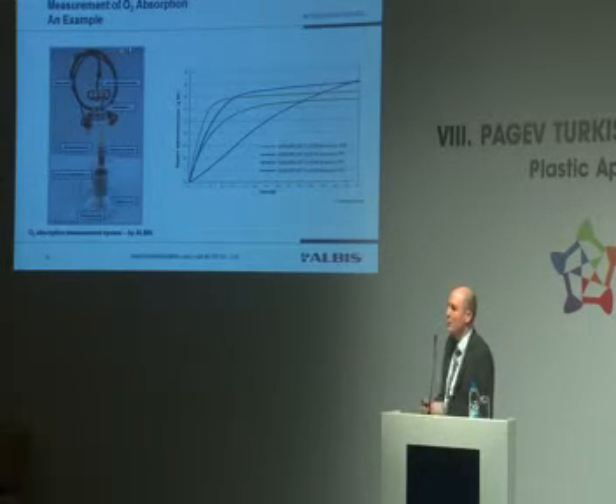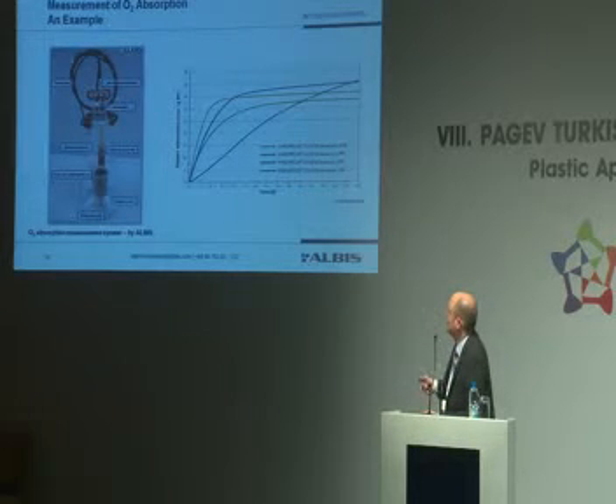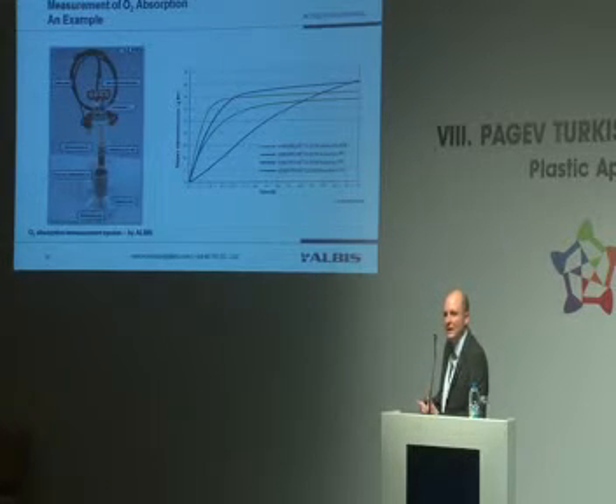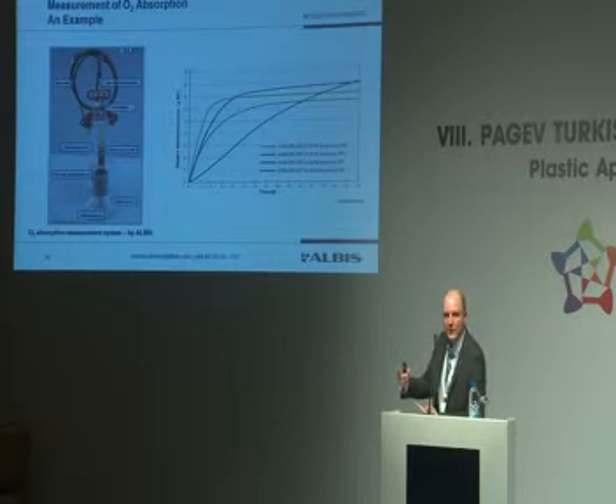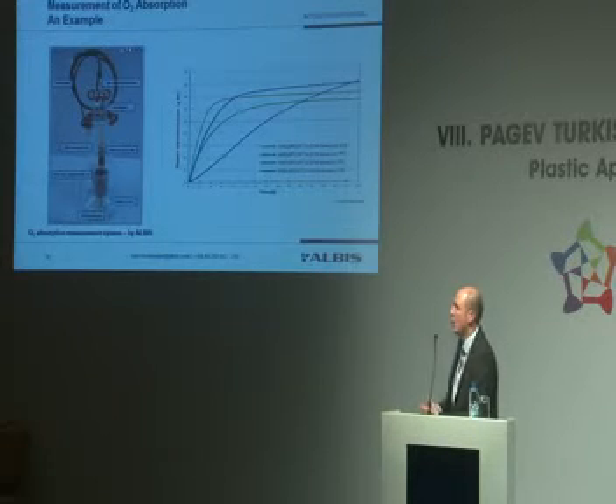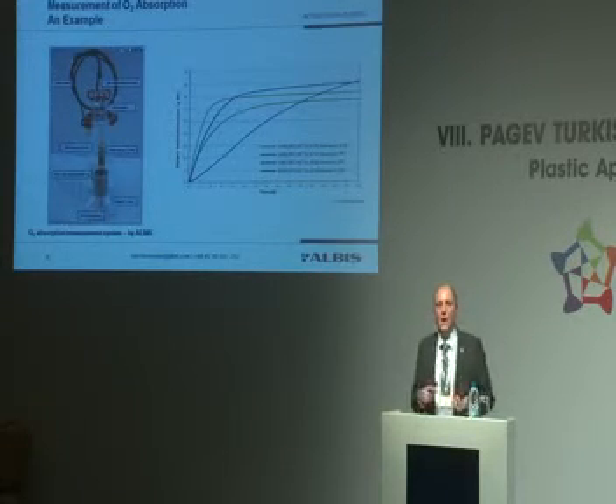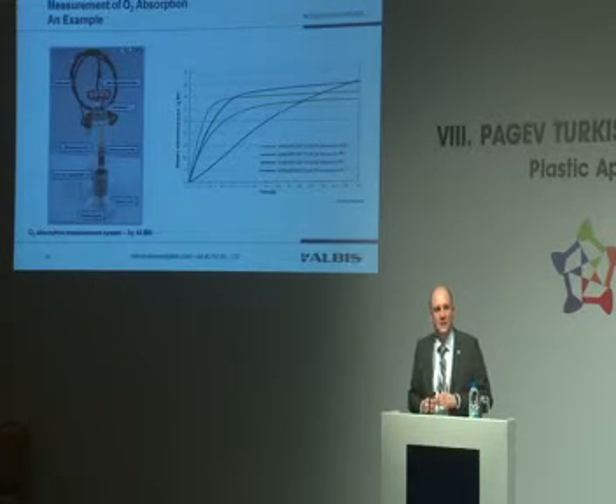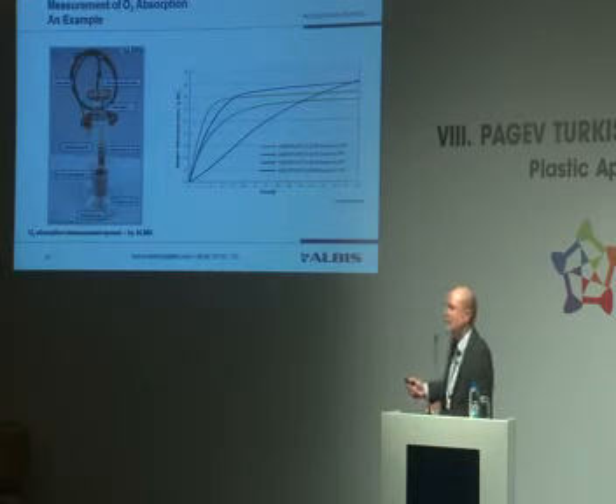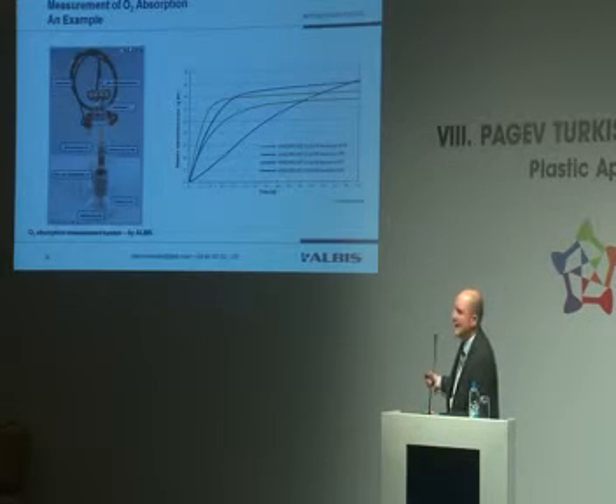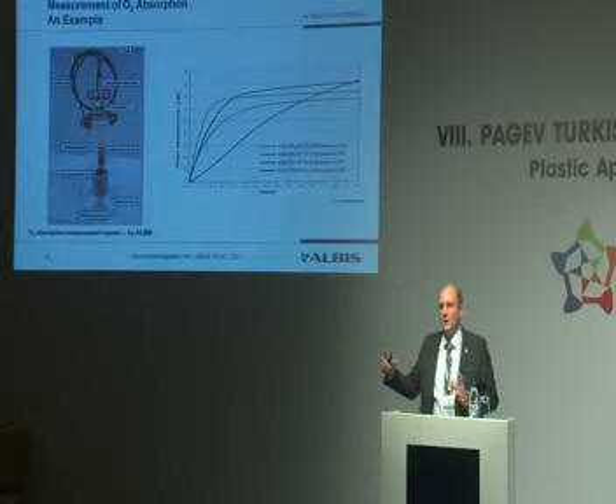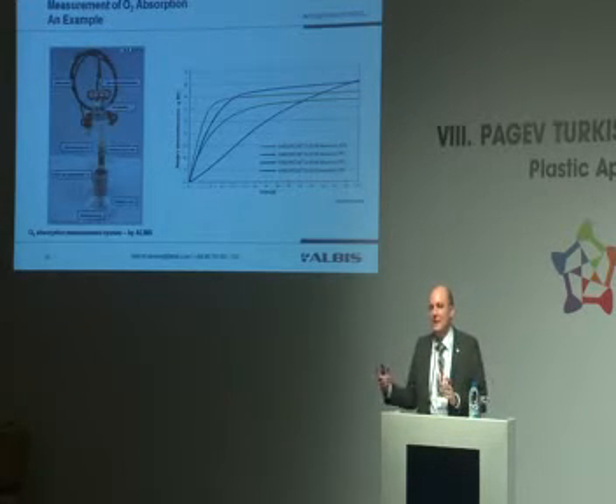And what also is rather obvious, this is ideal conditions, so high oxygen concentration in the testing device and high humidity levels. In real life, so in your final packaging or the customer's final packaging, of course the oxygen level can be lower, can be only 5%, and the humidity also a little bit less than the 100%. So this kinetic of the 8 days will prolong, so we will have 14 days, maybe 20 days of activity of the material.